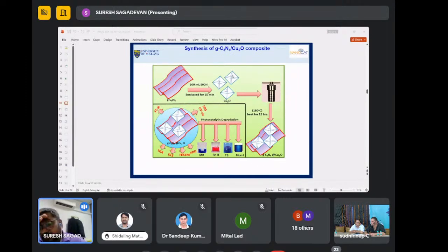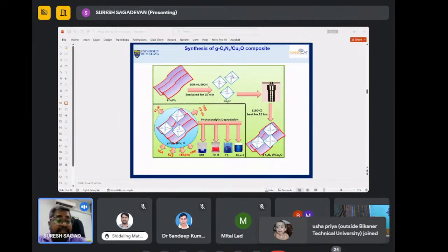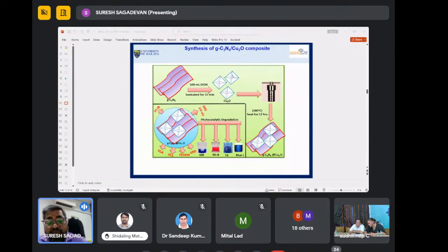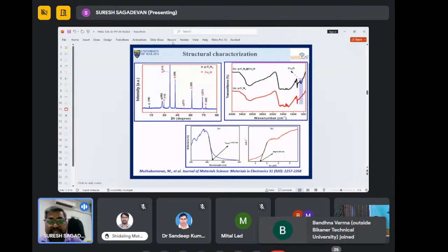After this, we studied the physical and chemical characterization like XRD, FESEM, DLS, DRS, and UV-visible. Our aim is concentrated on photocatalytic degradation. As I mentioned, we used very important industrial organic dyes: methylene blue, rhodamine B, thymol blue, and blue ink. First we have to confirm this composite material. How to confirm this composite material? By using physical and chemical characterization, especially X-ray diffraction and FTIR, which confirmed the successful synthesis.